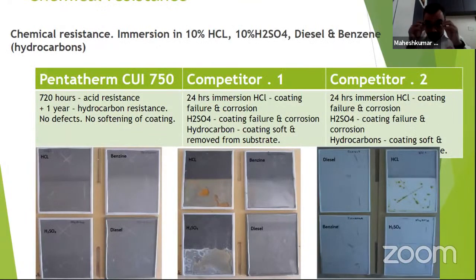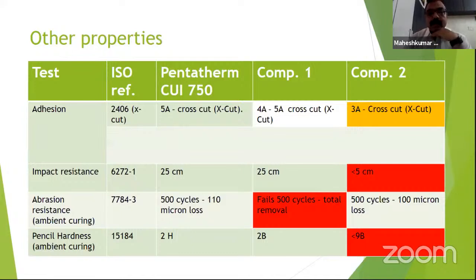Then we tested it for various chemicals, such as 10% hydrochloric acid and 10% sulfuric acid. We found that it is giving us hydrocarbon as well as temperature resistance and acid resistance in that particular area. Absolutely no issues. Then there were a few normal tests which are normally carried out at site. We followed them and found that it is meeting very high impact resistance as well as adhesion and hardness. The pencil hardness we found to be higher in terms of the CUI coating.